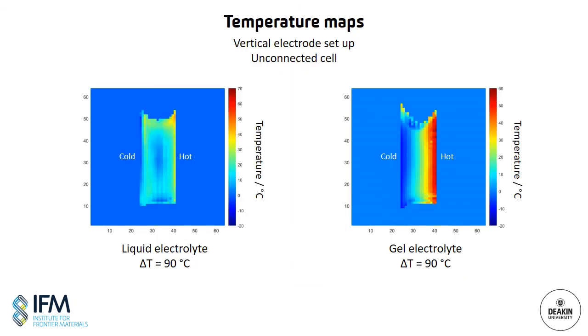So these images show temperature maps that we obtained from the vertical electrode cells with a liquid electrolyte on the left and a gel electrolyte on the right. These were generated just from the T1 maps, again obtained with the basic rare imaging pulse sequence. And in this case, the electrodes were unconnected to an external load, so there were no redox reactions occurring. And this allows us to assume that the concentrations of the two different cobalt oxidation states are uniform. And this means that the T1 value for each pixel in the image can be easily converted to a temperature via calibration measurements that we'd already made.